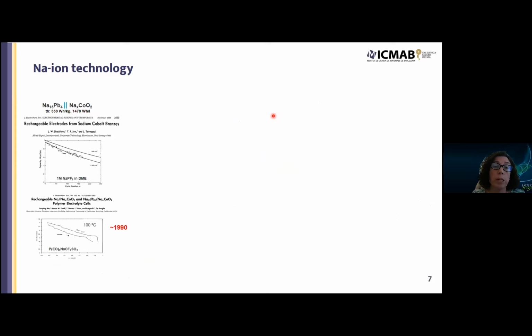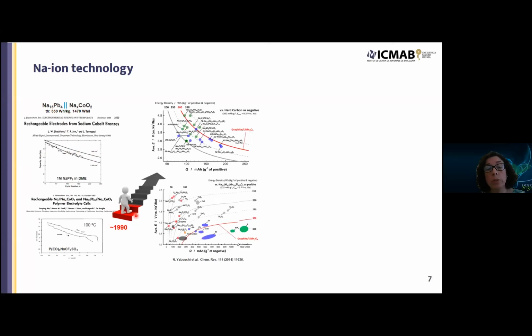So with respect to the sodium ion technology, which will be my first example, as you know, this technology is by no means new, and in the early days of intercalation studies, both intercalation of lithium or sodium or other metals were studied at the same time, but there were prototypes of full cells, full sodium ion cells using sodium cobalt oxide as the positive electrode and sodium lead alloy as the negative electrode. Cyclability was not very good at the time, but still. And of course, all of this was stopped when the lithium ion technology was commercialized. But then the topic was somehow rediscovered later on.